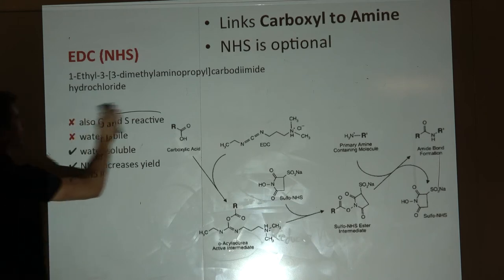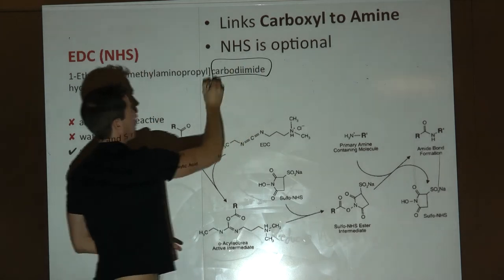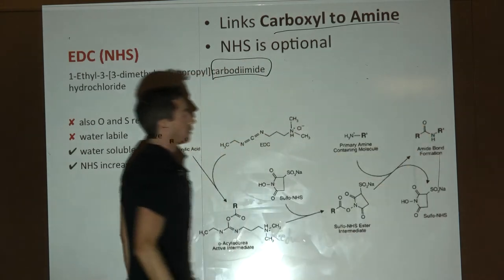EDC is a carbodiimide that links a carboxyl to an amine. Some side reactivity to oxygen and sulfur. Water labile - once you resuspend this, you don't want to keep it very long. You can combine NHS plus EDC together to increase the reactivity.